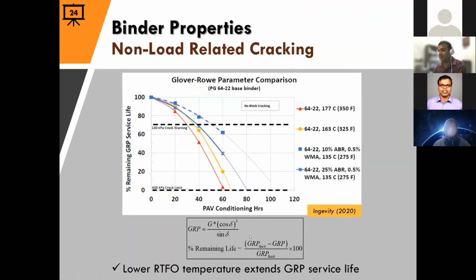This is another way of presenting the data. This is regarding non-load related cracking using the Glover-Rowe parameter, and this is from the literature. Actually, this is Ingevity's data, where they tried different RTFO temperatures, and at different PAV cycles they tracked how the Glover-Rowe parameter value was increasing. On the y-axis, it's called percent remaining Glover-Rowe parameter. The way the Glover-Rowe parameter was defined is that at 180 kilopascal, once you go beyond that, it's like a crack warning. And once you go beyond 600, that's the cracking limit. That's when cracking happens. So 0% life remains at 600 kPa.